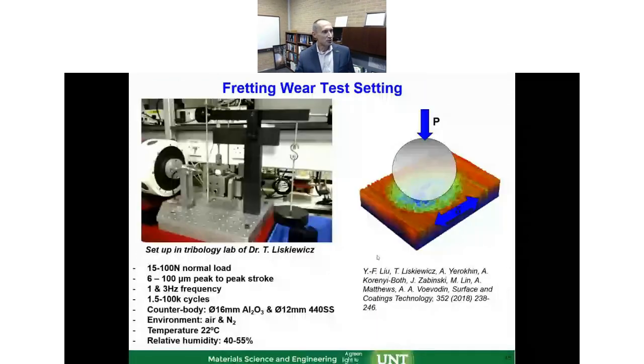And now we come back to testing, and we tested first in fretting wear testing with reciprocating motion. This is calibration work done with Thomas Liskiewicz. At that time he was at Leeds University and has the machine where you can apply the load and achieve the reciprocating motion. We're looking at the stick-slip transition. We also look at gross slip regimes when we have wear. I'll show you some of the gross slip regimes in a moment.